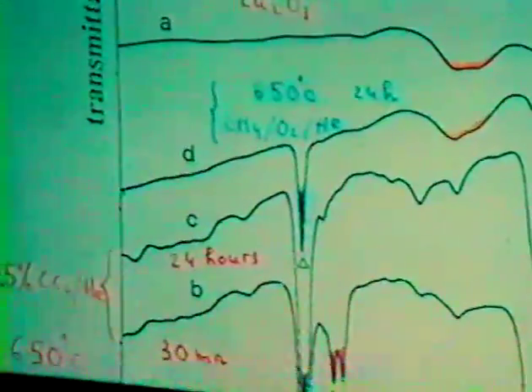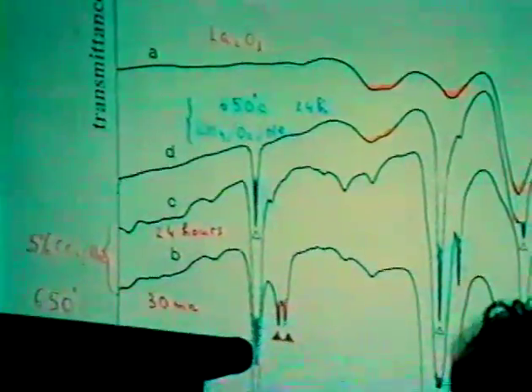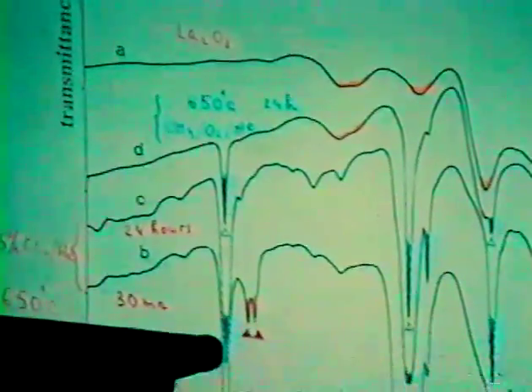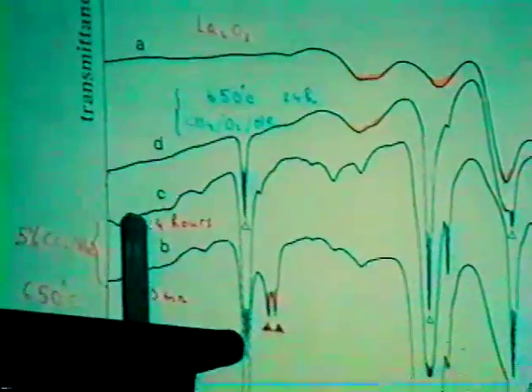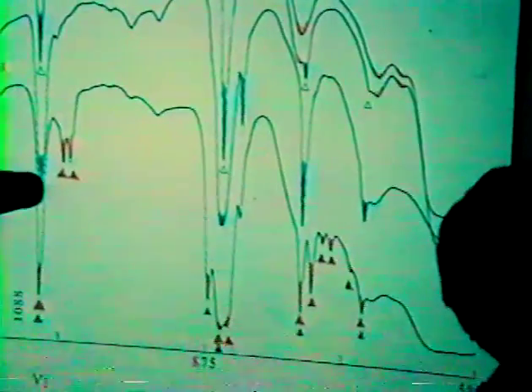Spectrum B and C represent the spectrum at the beginning, after 30 minutes, and at the end of duration, 24 hours. In red are represented type 1, the bands corresponding to the monoclinic polymorph, type 1A. In blue are represented the hexagonal polymorph. At the beginning of the experiment, you have a mixture of type 1A and 2, and at the end of the experiment, you have only type 2 oxycarbonate corresponding to the hexagonal structure.